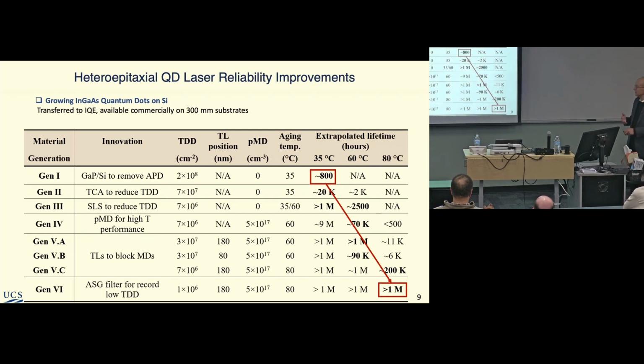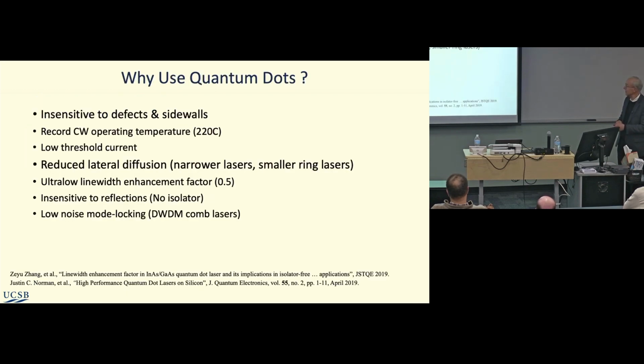There's a lot of things you do: thermal cycle annealing, strain layer superlattices, p-doping. Turns out you need to put in dislocation blocking layers, because when you grow on silicon, you may have low dislocation defects from all these things, but when you cool it down to room temperature, the strain builds up enough to generate misfit dislocations, and you have to deal with that. That's what these latest two things do, generation 5 and 6, to get it.